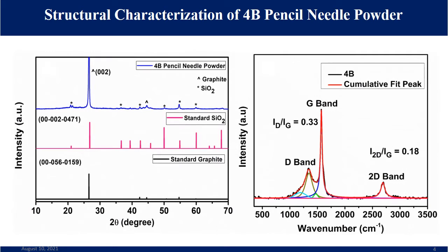The XRD of the pencil needle corresponds to the hexagonal crystal structure of the standard graphite. The significant peak of the 002 plane at 26 degrees may be attributed to the highly crystalline graphitic domains, and clay is an inherent material present in the pencil needles. The pencil clay consists of majorly SiO2, which has been identified and indexed. From this analysis, it is evident that it is a composite of highly ordered graphite and silicon oxide nanoparticles.